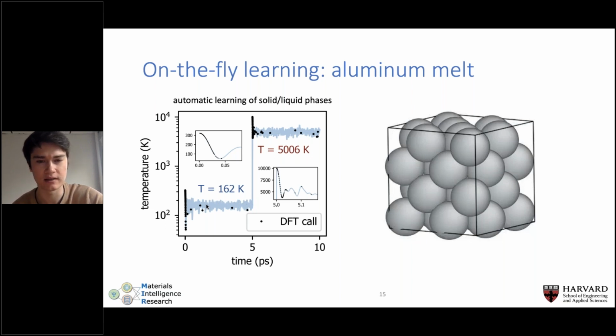Then the test to see if we could be sensitive to new environments was to increase the temperature to a very large value, to melt the crystal halfway through the simulation. You can see at 5 picoseconds here, we rescale the velocities all the way up to 5,000 Kelvin, which is way above the melting point of aluminum. And we check to see if the uncertainties are unacceptably high. You can see another cluster of DFT calls made immediately after we melt the crystal. So the model is sensitive to the fact that we've entered a new phase of matter, that now we're dealing with molten aluminum rather than simple FCC aluminum.